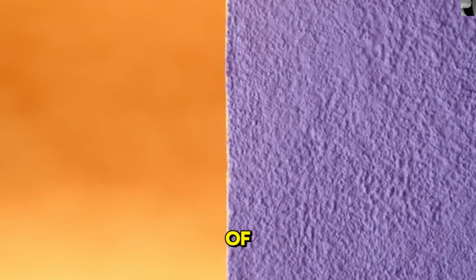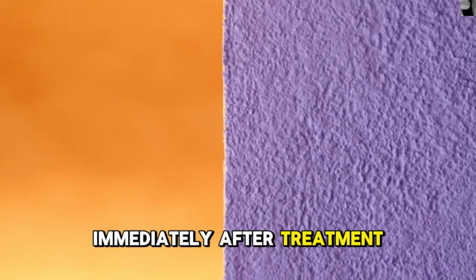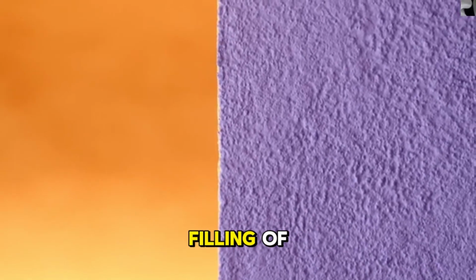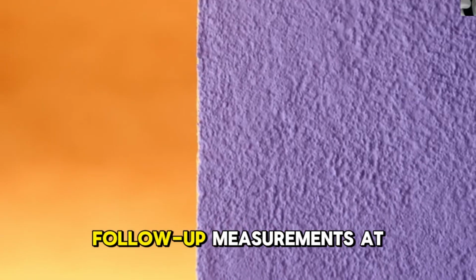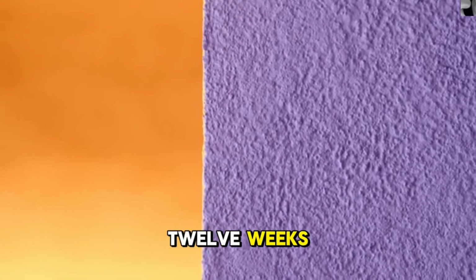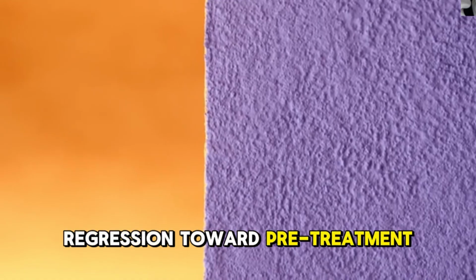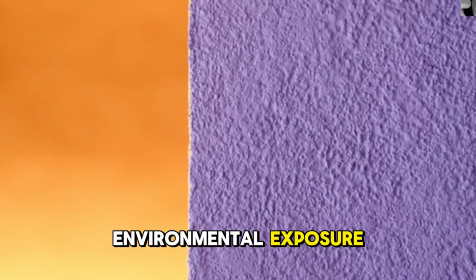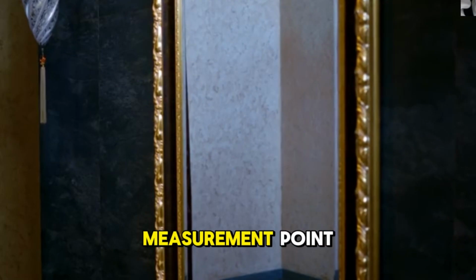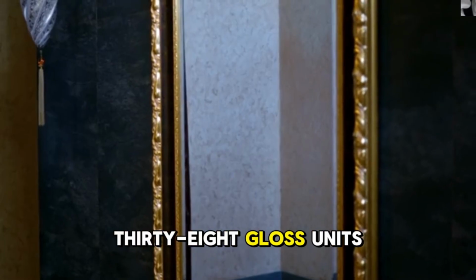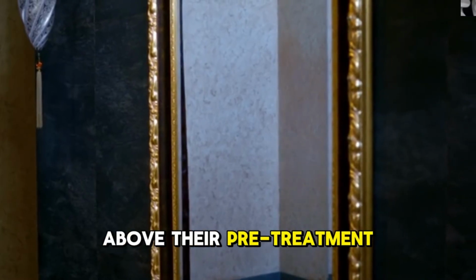The panels treated with commercial wax products showed an average gloss reading of 54 units immediately after treatment, a meaningful improvement attributable to the filling of surface microtexture with wax material and the smoothing effect this produced on light reflection. However, follow-up measurements at 4 weeks, 8 weeks, and 12 weeks showed progressive regression toward pre-treatment readings as the wax material degraded, was displaced by washing and environmental exposure, and ceased to fill the surface irregularities it had temporarily masked. At the 12-week measurement point, the wax-treated panels averaged 38 gloss units, only marginally above their pre-treatment condition.